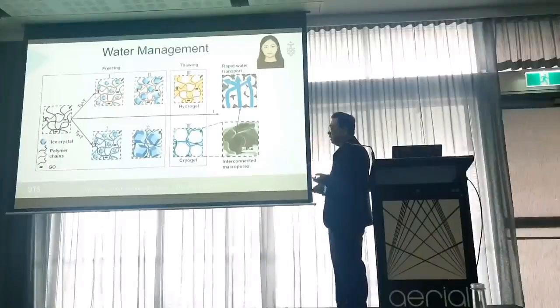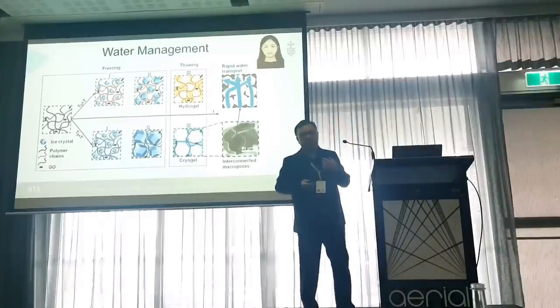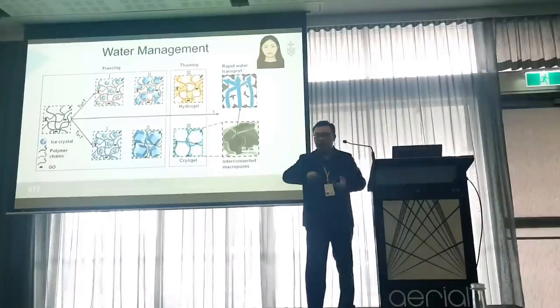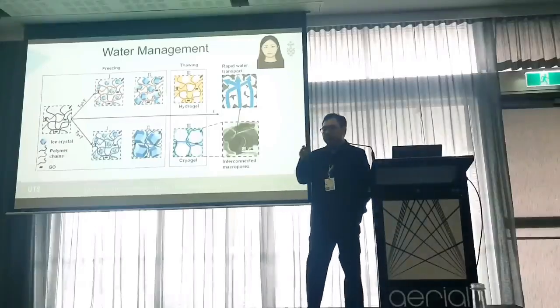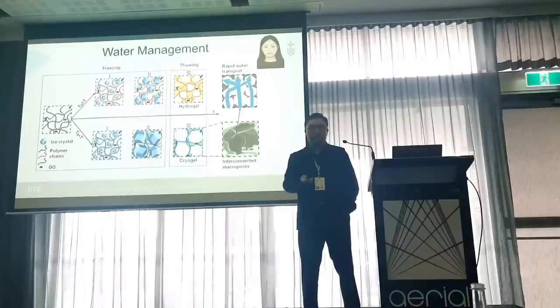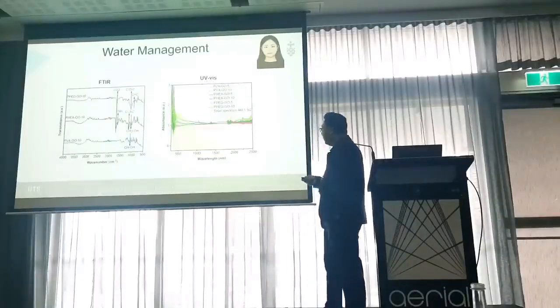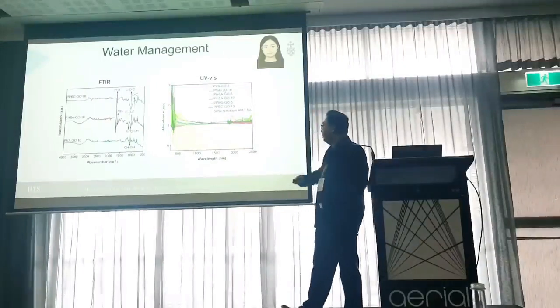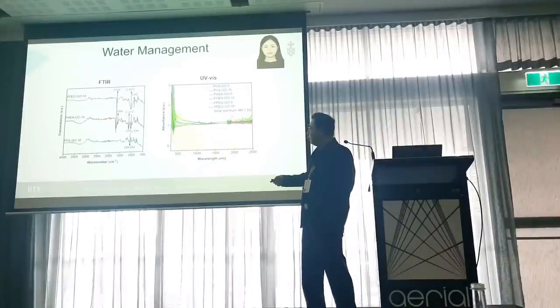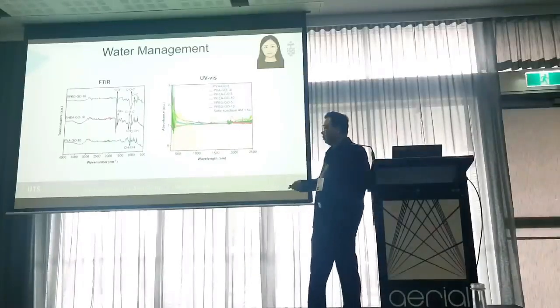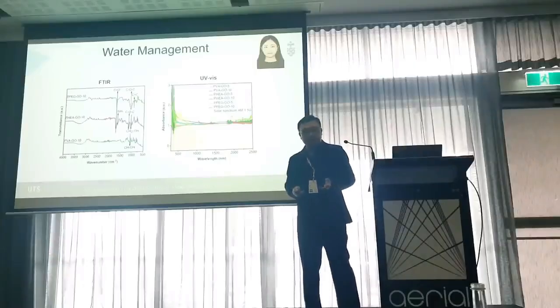And they are interconnected. And this structure, as I said, is expected to show rapid water transport, and eventually facilitate water evaporation. So we characterize these hydrogels by FTIR and UV-vis. You can see all the characteristics of the different hydrogels were observed, and all the hydrogels show a broad solar absorption spectrum.